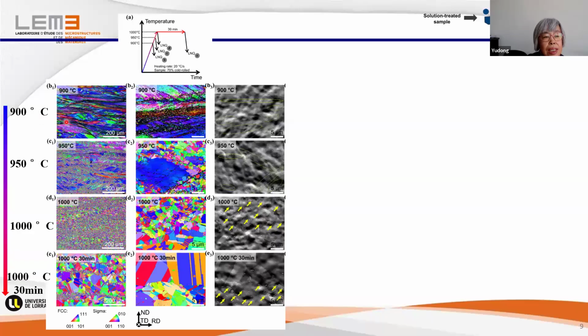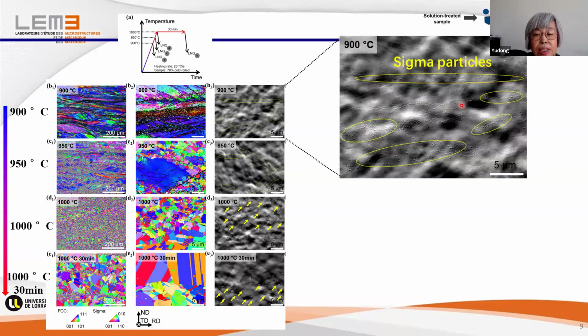And so we see at 900 degrees C, the material still preserves the morphology of the cold rolling state. Then we had a closer look at the slip bands, the dark area. We can see white dots already formed in these regions, and you see they did not form homogeneously throughout the microstructure, but are mainly located in the slip bands region. And we know these parts should be full of crystal defects.